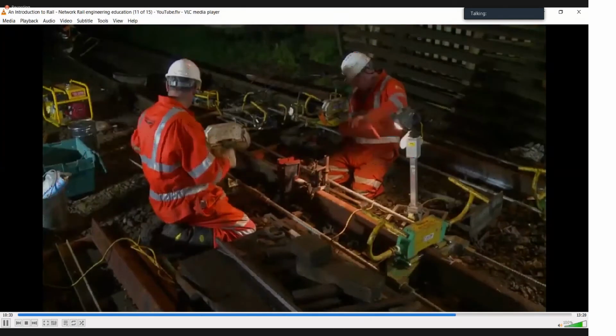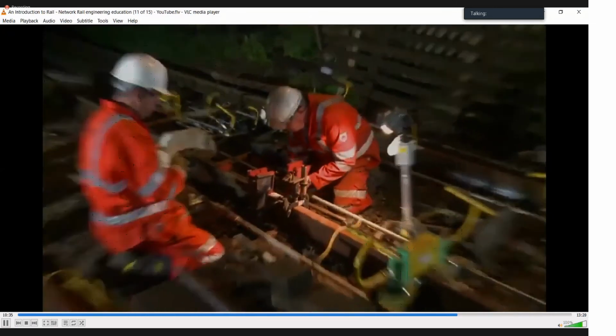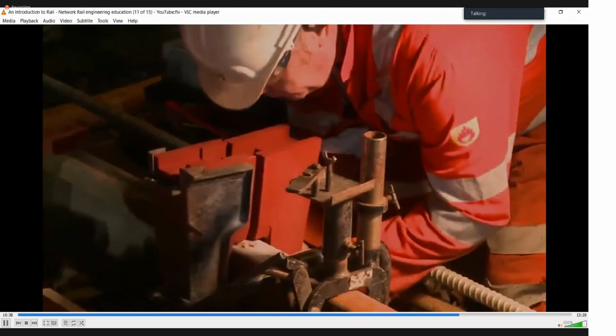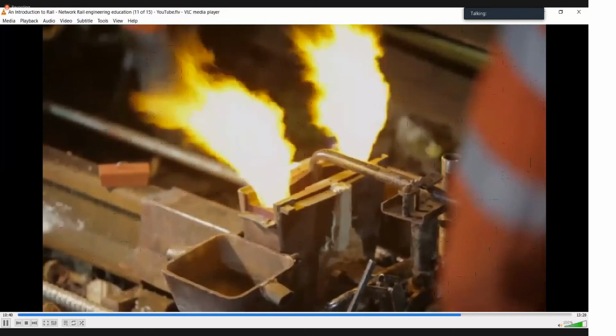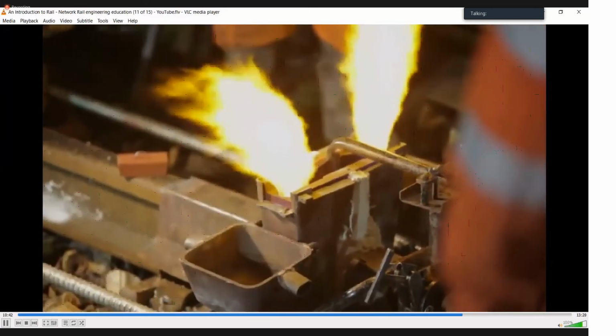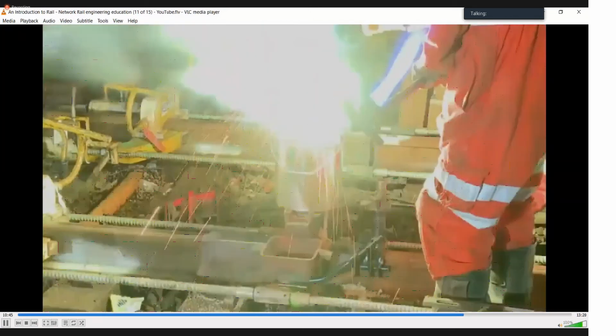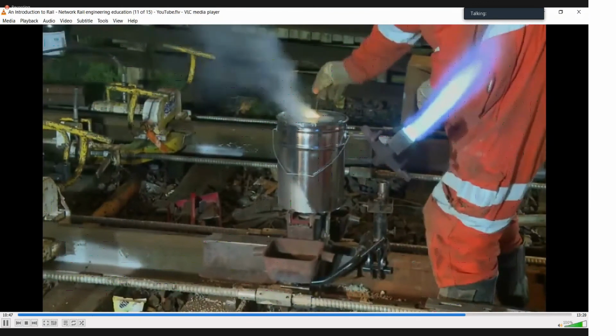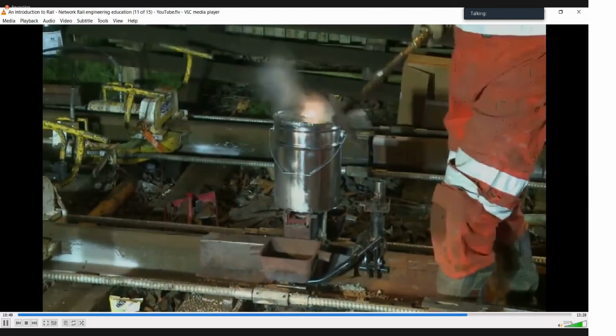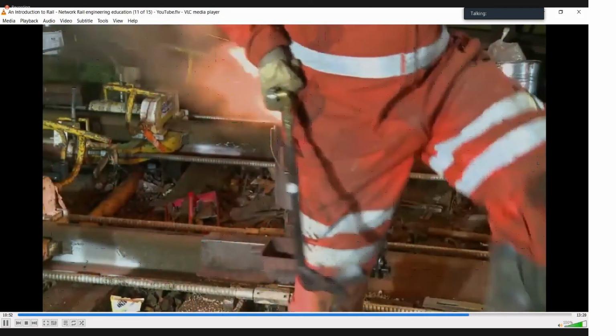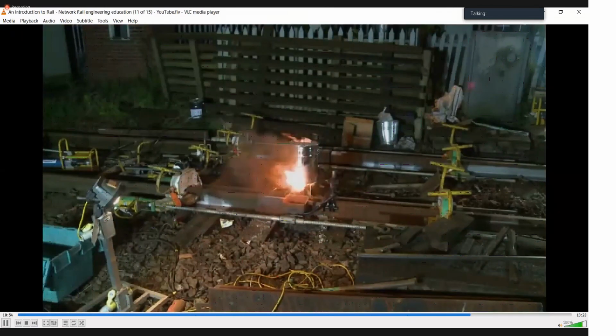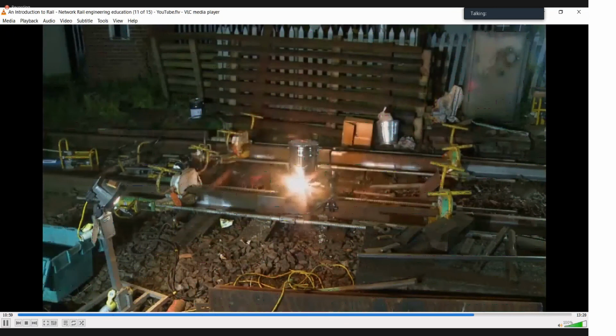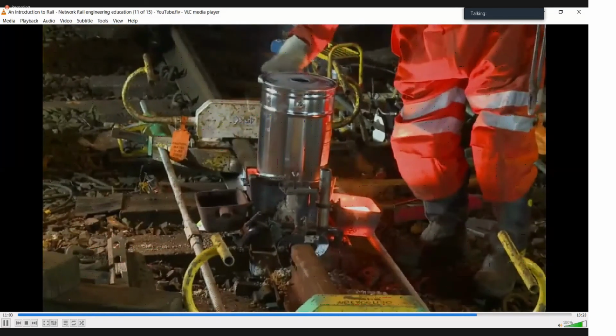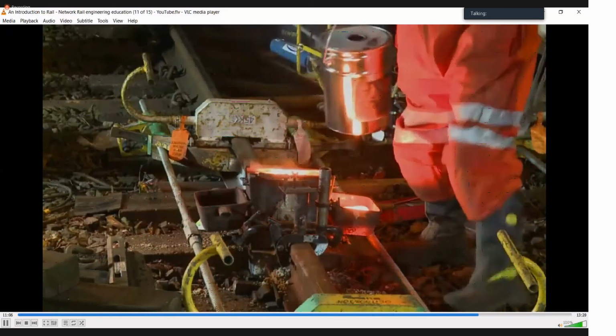First, the rail is clamped and pulled into position, and a mould assembled around the two rail ends to be joined. The rail ends are heated before welding to prevent the rail steel becoming brittle if it is allowed to cool too quickly. A crucible is placed on the mould. It contains iron oxide with specific alloying elements and volatile aluminium powder, which causes a chemical reaction that reduces the iron oxide into steel. The chemical reaction generates a huge amount of heat that melts the constituents to form liquid steel, which pours into the mould, fusing the rails together.